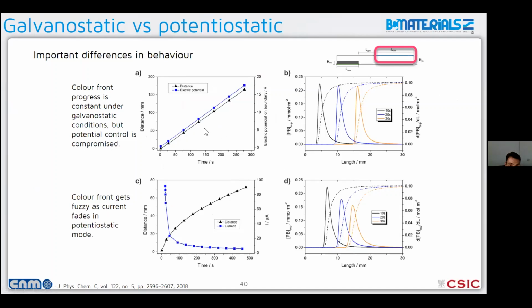We ran the model in galvanostatic and in potentiostatic modes, and what we saw makes sense, because when you run a constant current experiment, the rate of the process is constant. So you see the same profiles over a distance at different times, because the only thing that's changing is the potential of the electrode. But that's more or less what you expect. When you run a potentiostatic experiment, which is closer to the operation of the self-powered system, what you see is that the shape of the profile is changing depending on the IR drop.